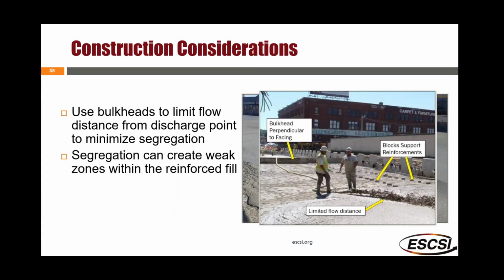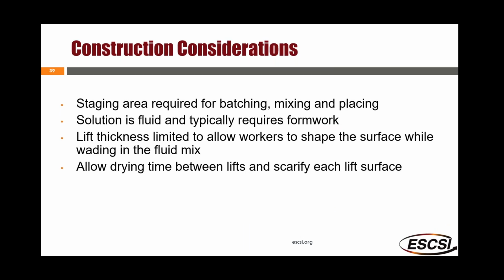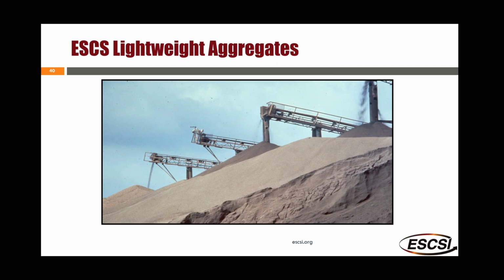Some construction considerations using this option are probably pretty obvious. Bulkheads need to be used to limit flow distance from the discharge point to minimize segregation. Segregation can create some weak zones within the reinforced fill, which should be avoided. A staging area is required for batching, mixing, and placing. The solution is fluid and almost always requires some sort of formwork. The lift thicknesses need to be such that workers can shape the surface while walking in the mix, and you should obviously allow drying time between lifts. So this brings us to ESCS lightweight aggregates.